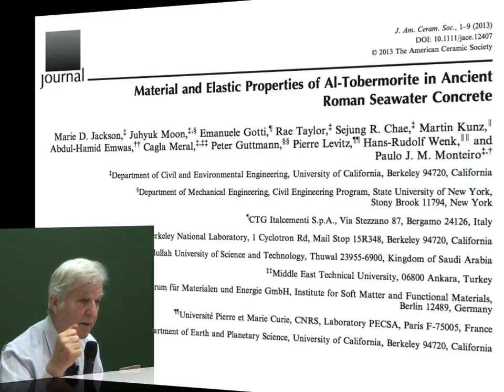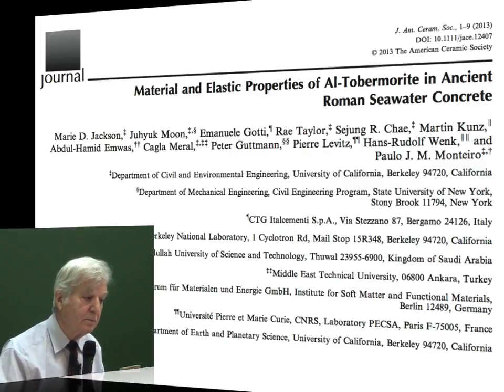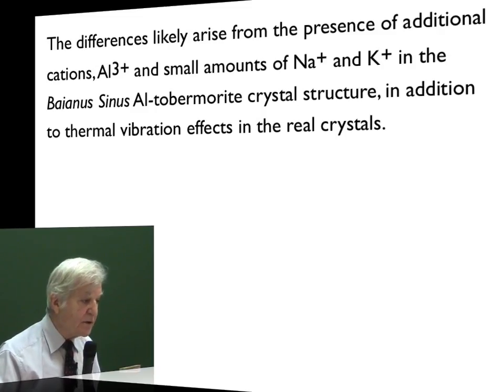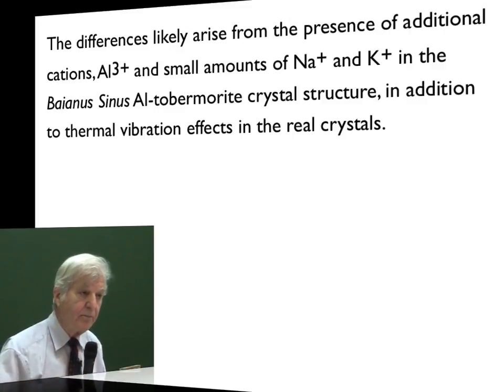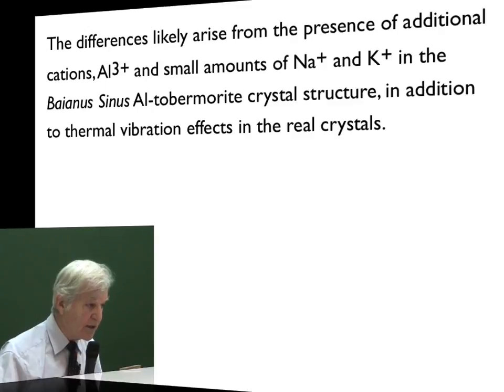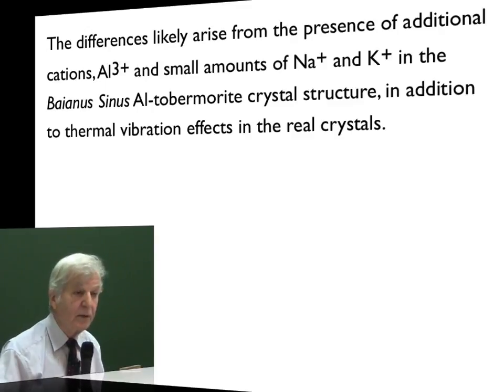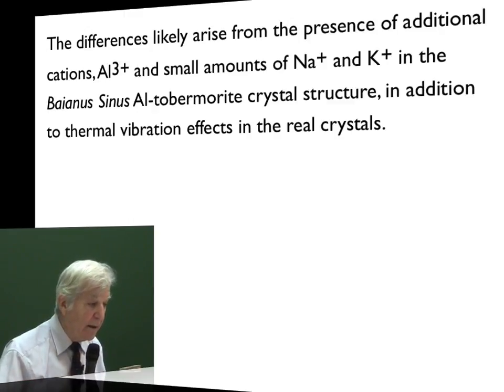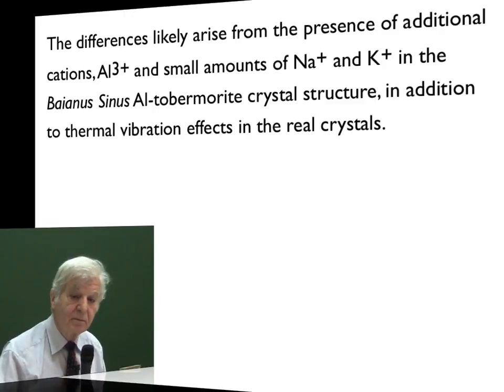So they studied very special pozzolanic material in the suburb of Pozzuoli, Napoli, and they found that in the mortar they had what they call aluminum tobermorite. This is what we also found anyway. But the fact is the following. So you see 1, 2, 3, 4, 5, 6, 7, 8, 9, 10 cement scientists working on this. The difference likely arises from the presence of additional cations. The difference between CSH, regular Portland cement, or regular lime-based cement, is Al3+ and a small amount of sodium and potassium. So one has aluminum, sodium, potassium in the system.